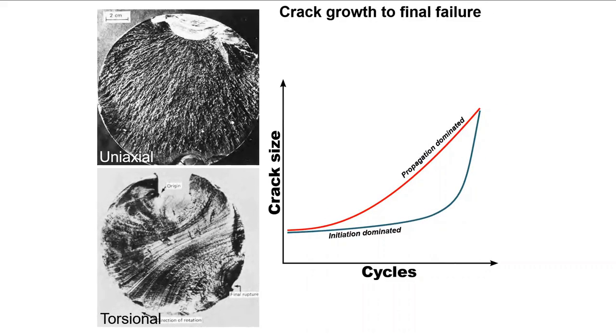Plotting the rate at which a crack will grow relative to the number of cycles for a given loading scenario, there are two main types of behavior depending on the material. Some materials have cracks which grow slowly and steadily until the final point of failure. Others are initiation dominated, which means that the overall fatigue lifetime is dominated by growing a crack to a critical point and then it accelerates. The top right fracture surface shows this type of behavior. The crack is grown slowly at first and then only required a few cycles to completely encompass the surface.